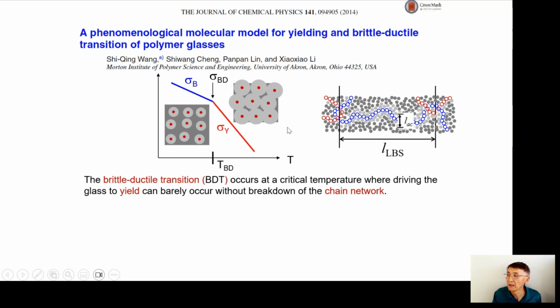So in some detail, basically, it is very logically concluded that the brittle-ductile transition is sitting at the Goldilocks temperature, below which the network fails to bring about enough mobility, and it will break down. And above that temperature, the network is robust and intact, and can bring about sufficient mobility. And this breakdown is understood in this language as the chain pull-out. So the blue chain, when you displace your polymer, if temperature is too low, cannot remain hooked with the red chain. They will start to pull out.